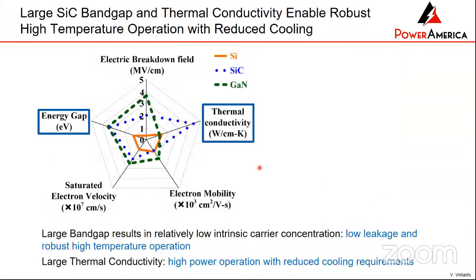And then looking at this graph one last time, you can see that the thermal conductivity of silicon carbide here in blue is much higher than the thermal conductivity of silicon, which is the competitor, and GaN for that matter. So the fact that you have higher thermal conductivity means that you can operate at higher temperatures, okay? And that's very, very important because a big part of the power electronics system is the cooling mechanism. So then cooling becomes a lot simpler to implement and a lot cheaper to implement.